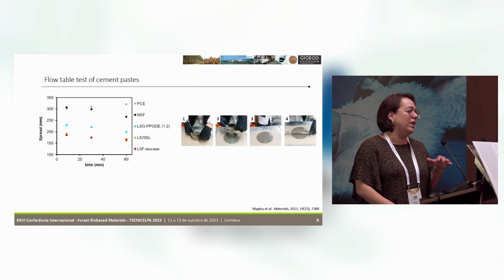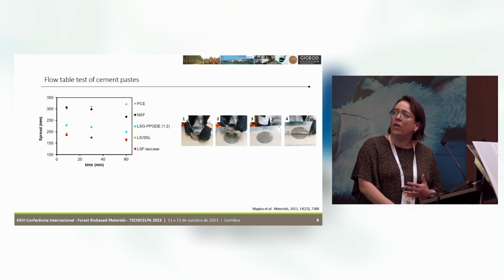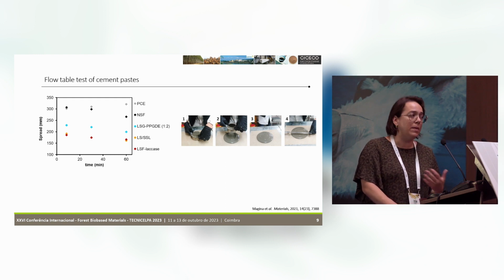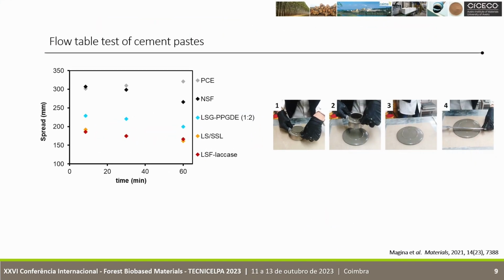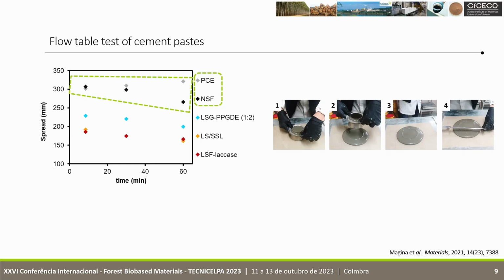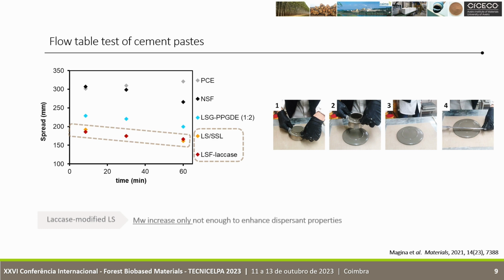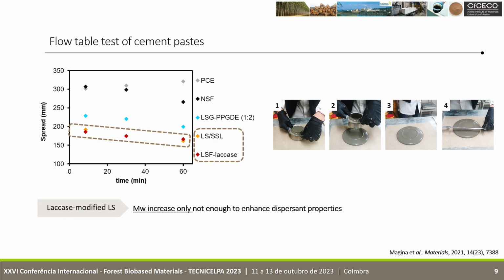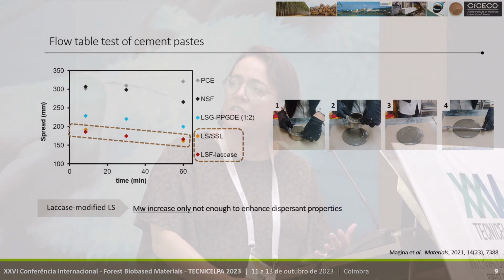These modified products were then tested at CICECO, and the fluidity of cement pastes was determined by measuring the spreading of these pastes. Superplasticizers were tested for comparison, and you can see that they gave the best results, especially the polycarboxylates. Lignosulfonates modified by laccase treatment gave results very similar to unmodified lignosulfonates, showing that increasing molecular weight without increasing the number of ionizable groups is not enough to enhance the dispersant properties of these products.